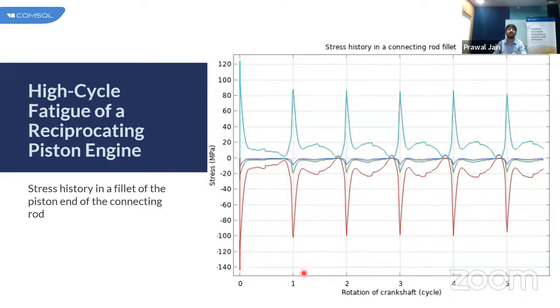Here the stress history is dominated by the third principal stress, since the connecting rod that we just saw is in compression, and the other two principal stresses are so small that the stress state at the fillet can be considered uniaxial. We can see that one of the stresses is significantly higher than the other two. Therefore, the third principal stress can be taken as the amplitude stress in the Basquin relation for fatigue life calculation. We could also use the von Mises stress, but as we just discussed, in this case we can use only the third principal stress for calculating fatigue life.